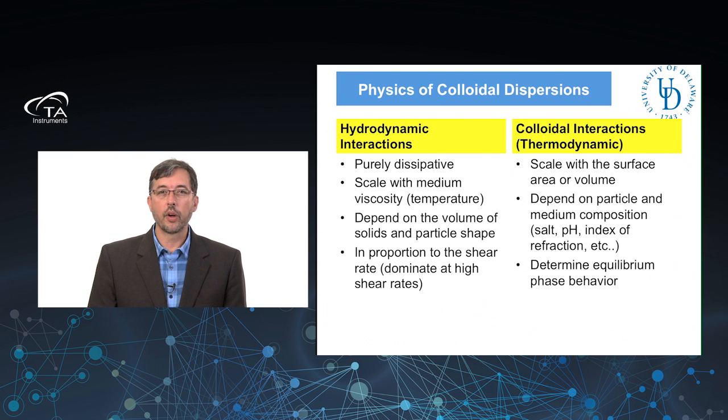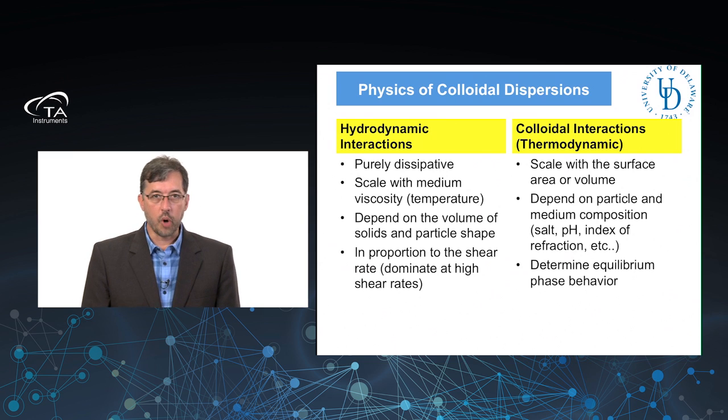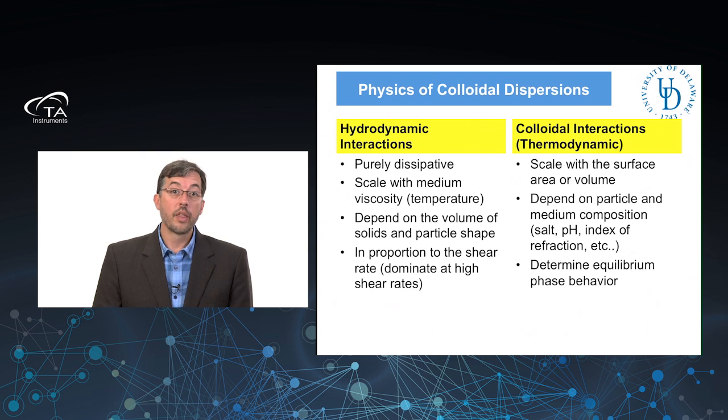First, we have hydrodynamic interactions. And where do those come from? Well, we have a solvent. We have solid particles in it. So as soon as I shear a colloidal suspension, the particles, they don't deform, right? And so the fluid has to flow around the particles. Furthermore, if I move a particle, right, by Brownian motion, that particle has to displace the liquid to move, which means it creates a flow field, and that flow field interacts with the other particles. So these are very strong interactions propagated by the presence of the solvent. They are not there in many other systems, such as atomic systems, where you have a vacuum between the particles. So they're essentially characteristic of colloidal suspensions.